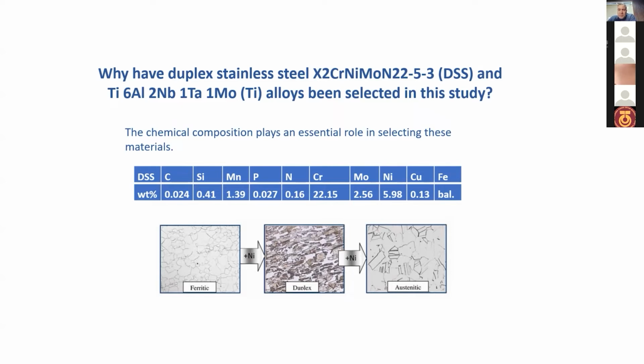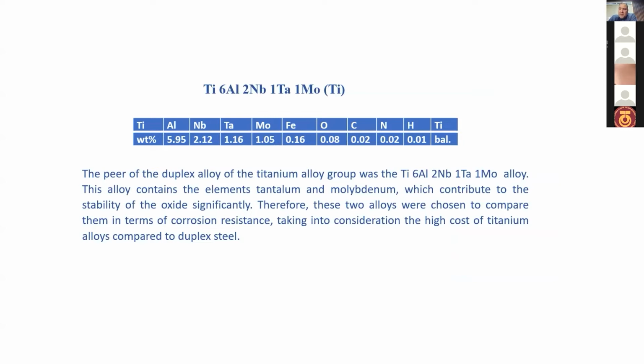The higher content of nitrogen in duplex compared with conventional stainless steel contributes significantly to increasing chloride corrosion resistance. Now, the counterpart of the duplex alloy from the titanium alloy group was the titanium 6 aluminum 2 niobium 1 tantalum 1 molybdenum alloy, and this alloy contains the elements tantalum and molybdenum, which contribute significantly to the stability of the oxide. Therefore, these two alloys were chosen to compare them in terms of corrosion resistance.